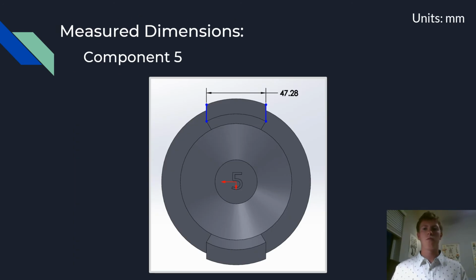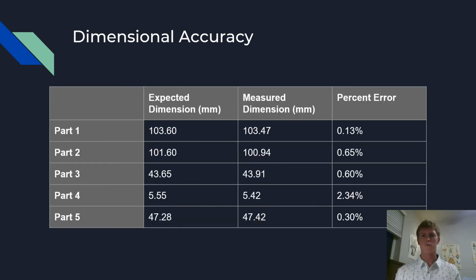On Part 5, the width of the dovetail pin on its base was measured. This pin fits into a slot on Part 1, which ensures that the lid stays in place until the box is unlocked. The fit of this joint determines if the box can be opened before the unlocking sequence is completed. The values measured from the printed box were compared to the dimensions specified in the computer models used, and a percent error was calculated. Almost every measured dimension was within 1% of the desired value, except for the diameter of the pins on Part 4.